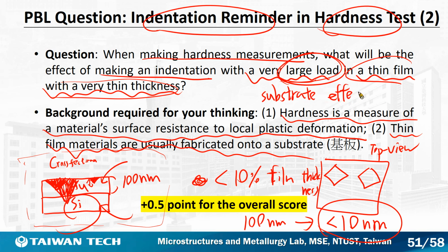If you have thin film materials, you need to pay attention to this substrate effect. And also, you cannot make an indentation too close to a pre-existing one.